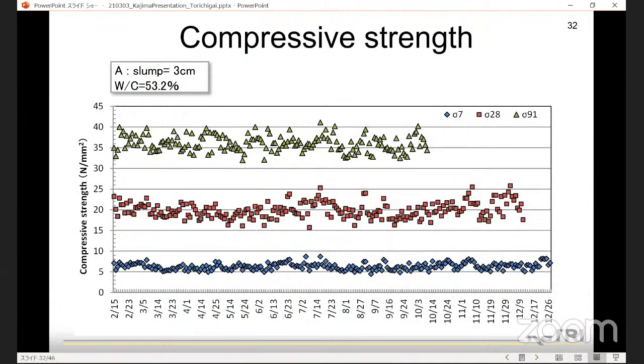And this slide shows the variation in the compressive strength of concrete in the outer part. At 91 days, there is a variation of about 5 to 10 Newtons per square millimeter.